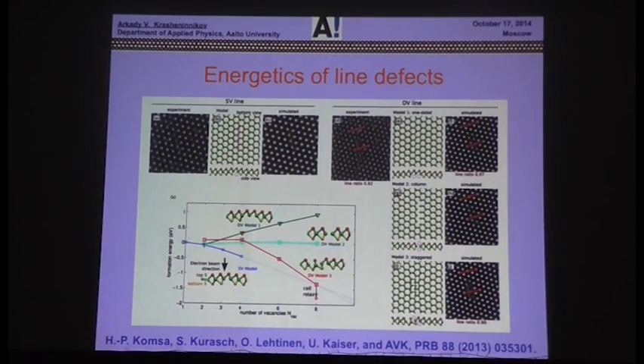Of course, the first aspect is vacancy lines, and we tried to analyze the energetics when two vacancies meet and form line defects. For two structures, like a single vacancy line or vacancies on different sides, in two cases the energy goes down, and based on our structures, we simulated the TEM images and compared to experiments. These are exactly the structures experimentalists see in their TEM images. So basically, these structures can be explained through formation of vacancy lines.